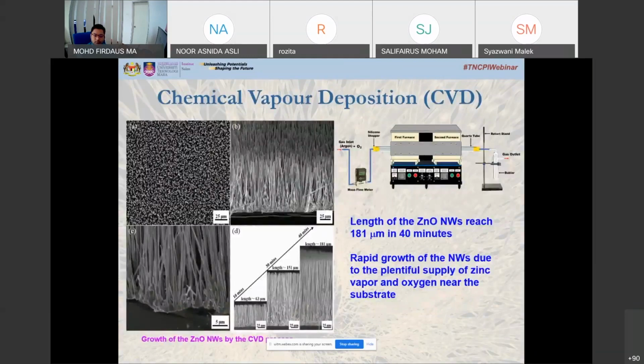Now we go for the next method, which is also quite famous. We are also using this method in our lab, which is chemical vapor deposition. Chemical vapor deposition is an attractive solution for synthesizing zinc oxide nanowires at large scale without incorporation of catalyst, compared to the previous method, which uses a catalyst to form the nanowires. So the catalyst-free approach ensures the production of high purity zinc oxide nanowires compared to the VLS growth approach.